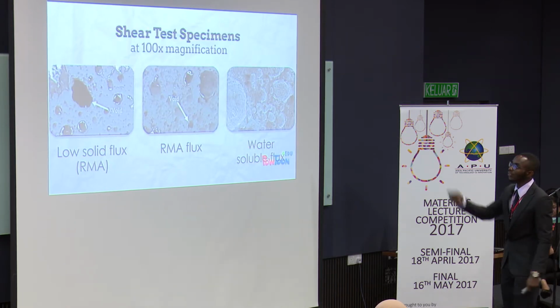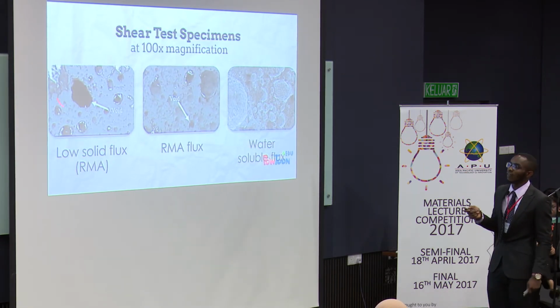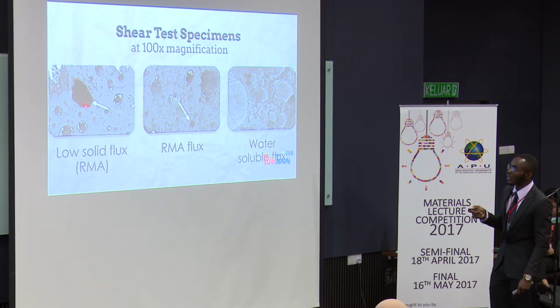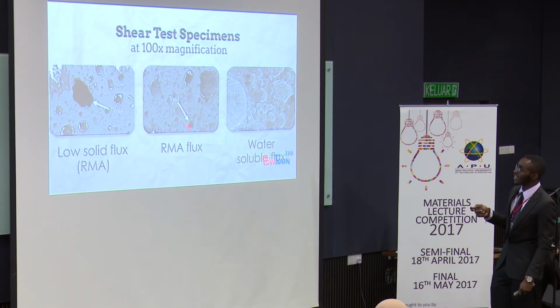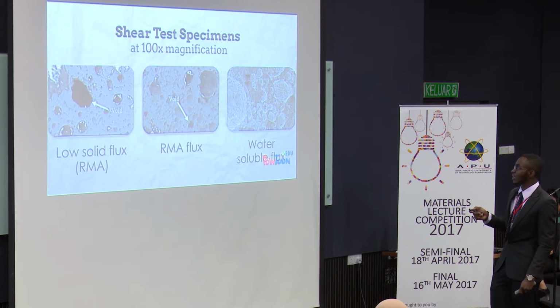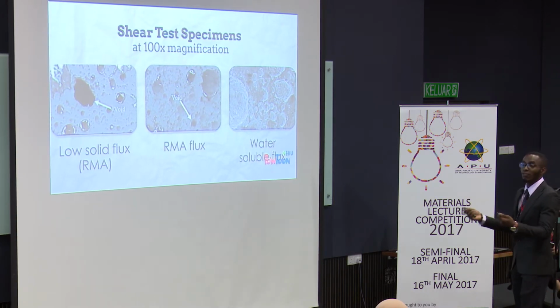We then went further to 100 times magnification, where we see voids now. And then the voids, as we can see here, are really huge. We see a tiny void on the RMA flux. And then on the water-soluble flux, there are no voids whatsoever.